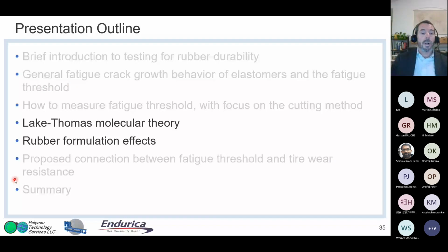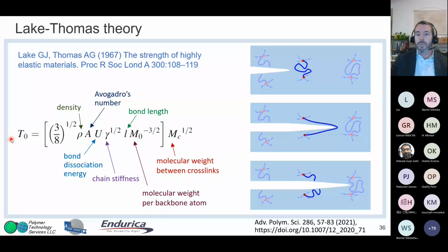So that brings us into this Lake Thomas molecular theory and some rubber formulation effects. They kind of dovetail nicely together. So Lake and Thomas, again, taking this picture that in order for a crack to move through rubber, the minimum energy required is energy required to break all the polymer chains. So this chain is already broken, and the first thing that happens is the crack stretches the chain between the crosslinks. One of the assumptions in their approach is that these crosslink points don't move. Maybe that's not realistic, but again, that's one of their assumptions. So first thing is the crack has to become stretched.